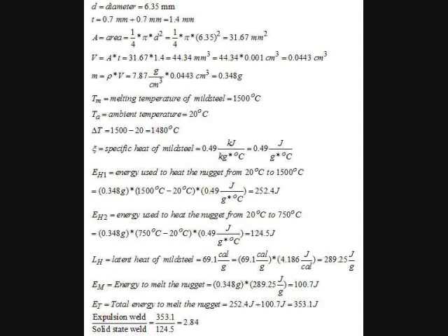We only consider the housing as a cylinder. Its diameter is 6.35, which is the cap diameter, and the thickness is 1.4, which is 0.7 plus 0.7, 1.4 millimeter. Area is 31.67 millimeter square. The volume is 0.0443 cubic centimeter. This calculates out to a mass of about 0.348 gram.